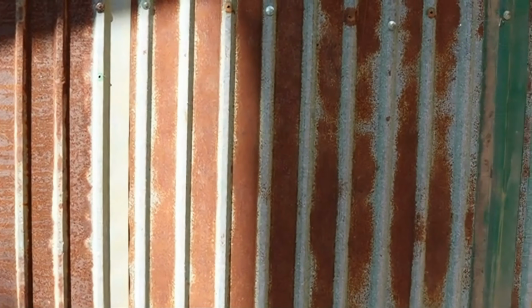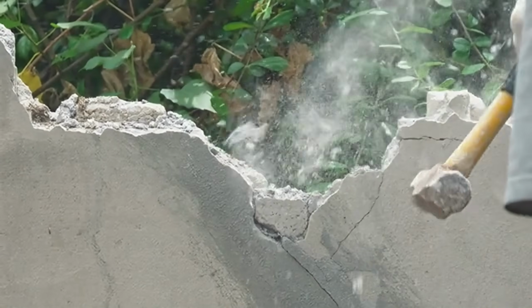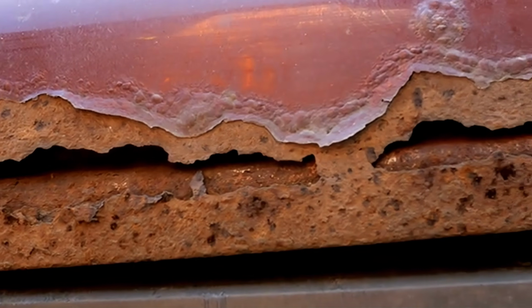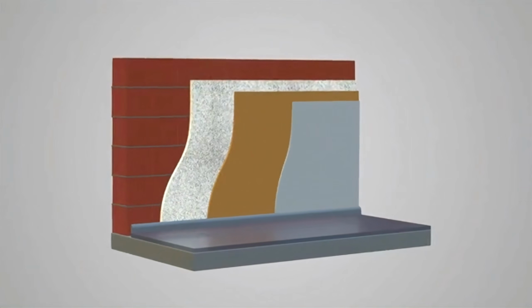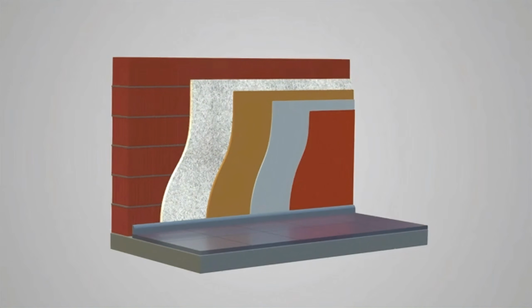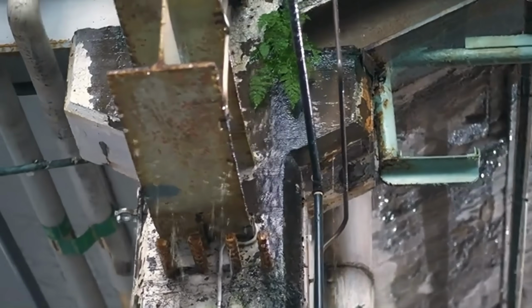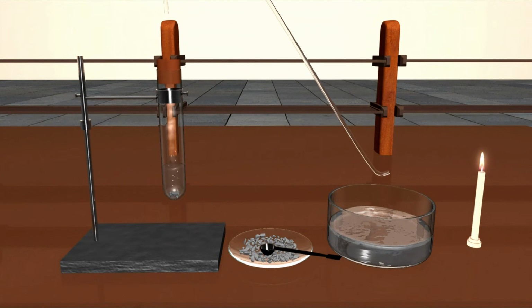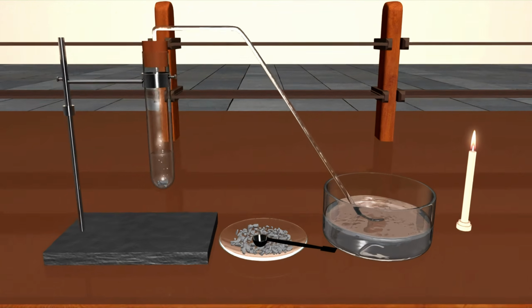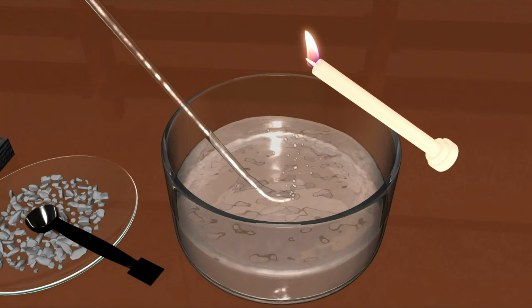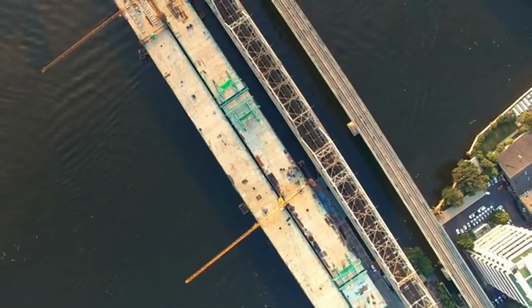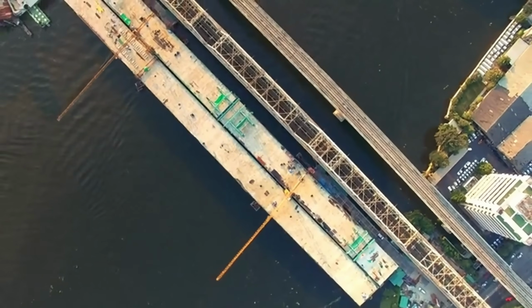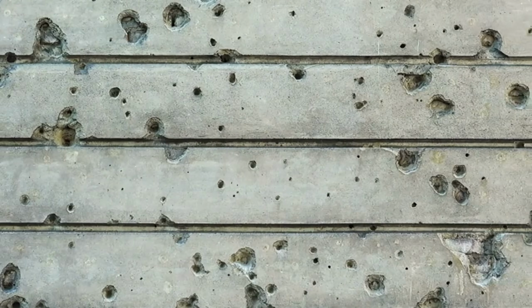Once the protection is gone, the steel begins to corrode, and here's the part that destroys the structure. Rust occupies substantially more volume than the steel it came from. Estimates vary with conditions, but the expansion is large, and it happens inside a material that has nowhere to go. So the rusting bar swells and pushes outward, and it cracks the concrete from the inside. Those cracks let in more water, more oxygen, and more salt, which accelerates the corrosion, which produces more expansion, which produces more cracks. That is why you see concrete spalling off bridge soffits and car park decks with rusty bars showing through. It is not that the concrete failed, it is that the steel inside it grew.